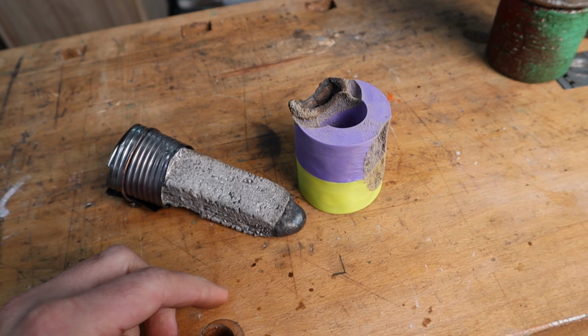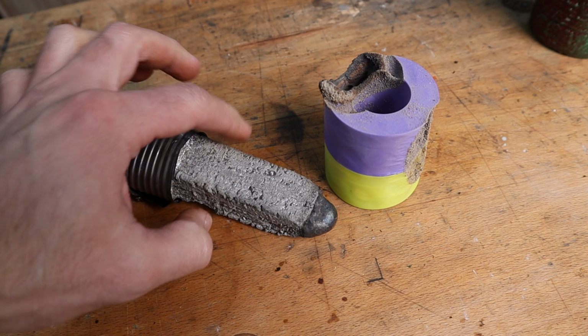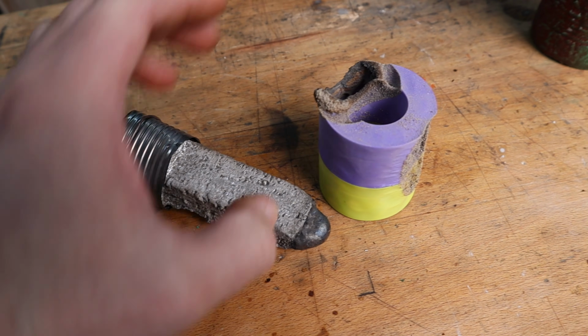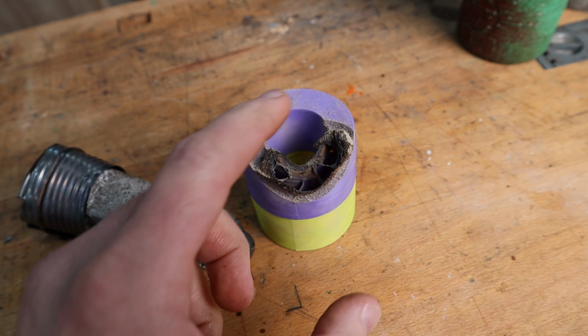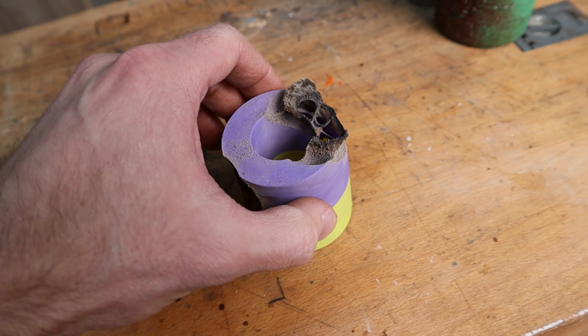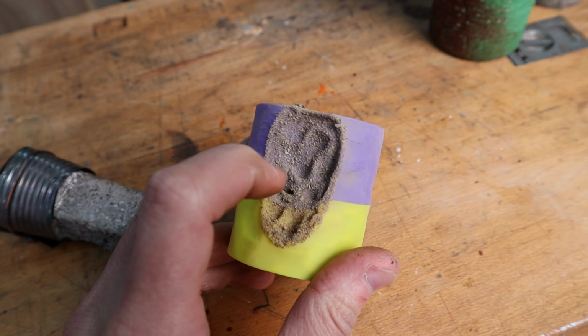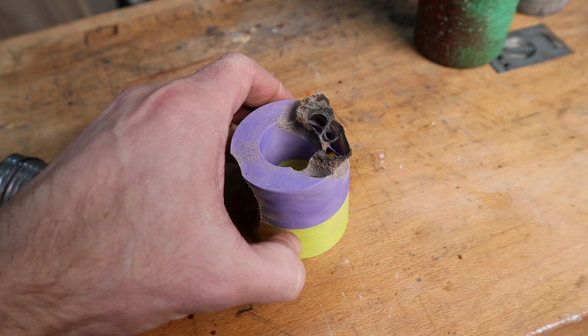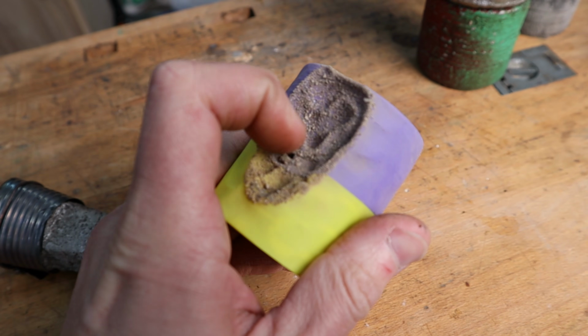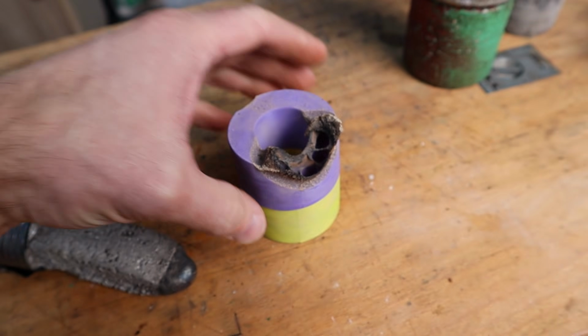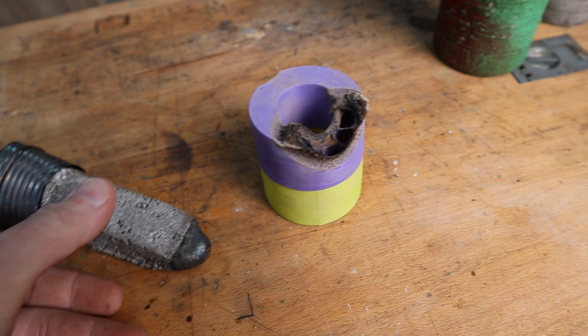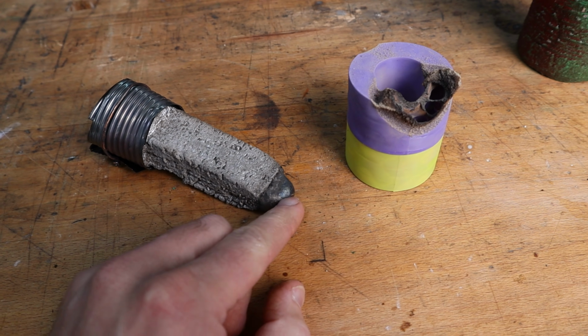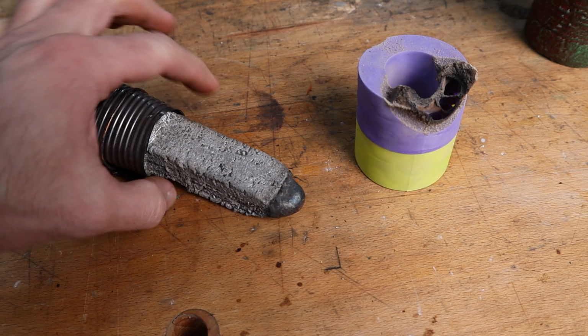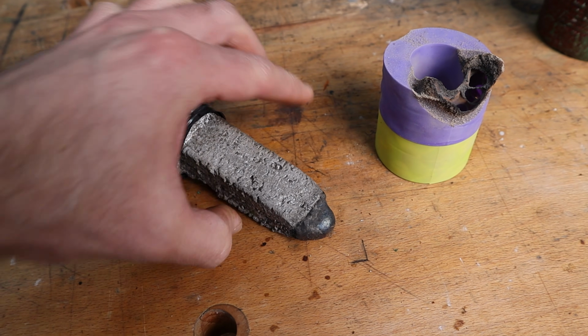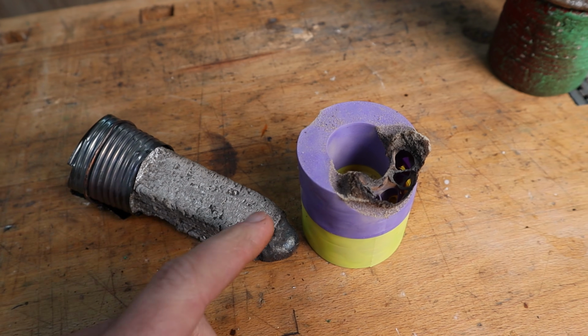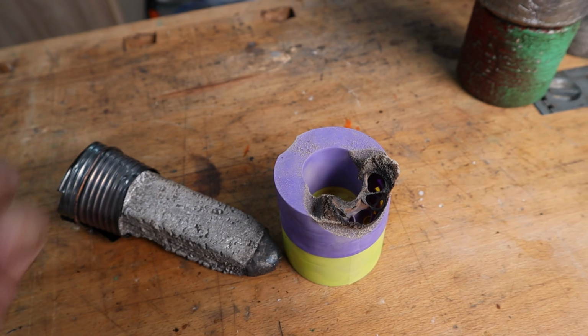So here we have the PLA version of the lost foam method, and the foam part did really well. When it came down and made contact with the plastic, I think what's happened is it's created a gas, and you can actually see here it's melted a portion of this side, maybe because of the gyroid infill. That's where the gases were able to get to really easily. And I think it couldn't really escape, so instead it blocked any more molten metal from getting in there. So I could tell when I was pouring, it didn't seem like much metal was going in. So I had a lot of hope for this one, but unfortunately it was just a complete fail.